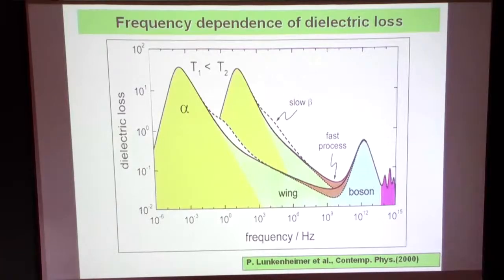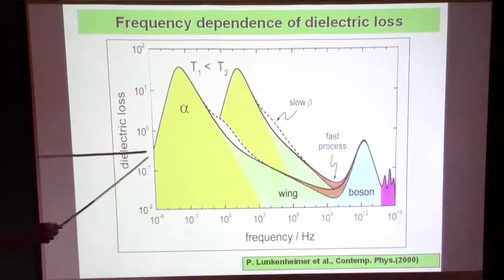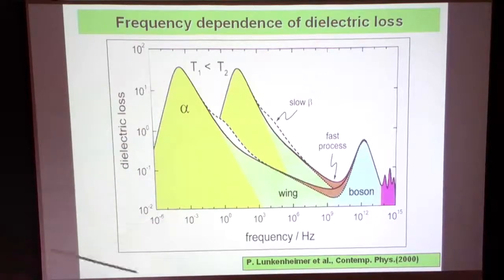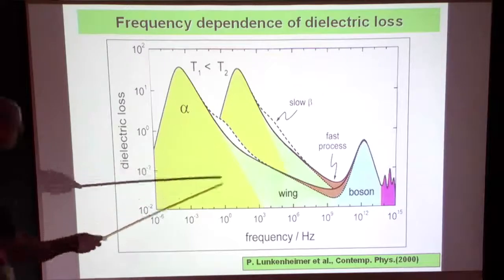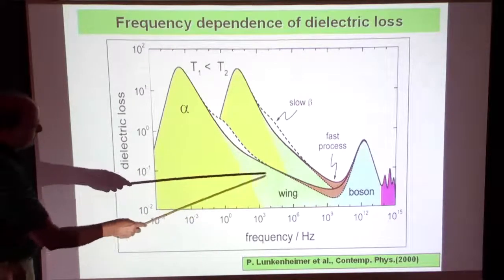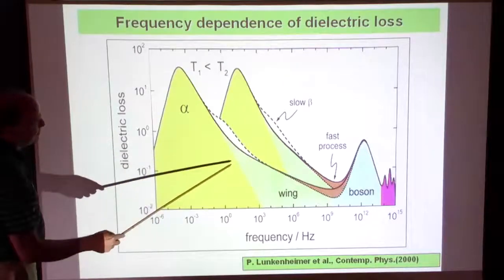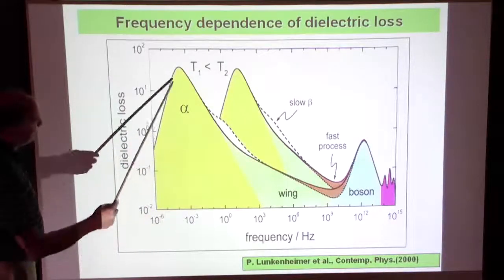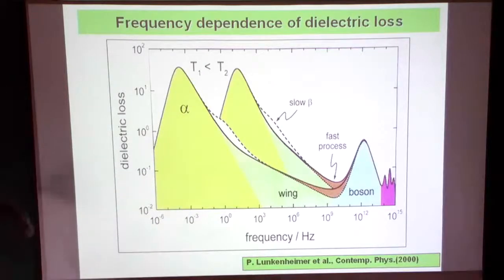And what you see, this is very general, is several types of losses if you excite the system. One is called the primary or alpha relaxation, at temperatures around the glass transition temperature, something related to the viscosity. Then at far higher frequencies we have what we call the wing or the slow beta processes, which show up as an asymmetry of the alpha peak to the high frequency range. That is what I call the beta relaxation or Johari-Goldstein modes, and I will show you what we know about it right now.